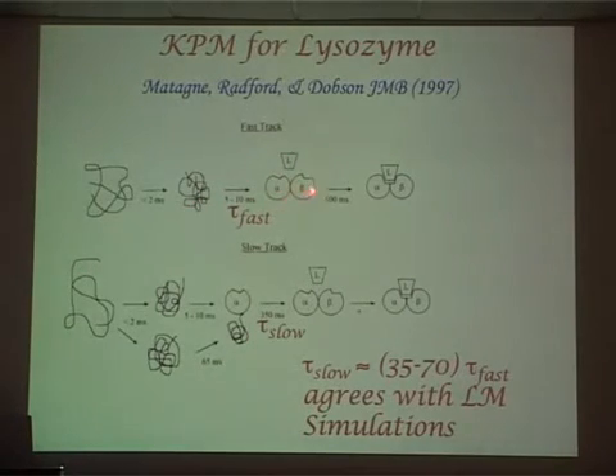Actually, Kiefhaber was the first to do this, but this is an experiment from their paper in JMB in 97. They looked at lysozyme folding, from the unfolded state to the folded state. They do find these fast track molecules, and this is just ligand binding, so you really worry about this fast time scale, which is about 10 milliseconds, and you see that the slow one is about 70 times greater, and therefore this is exactly what we find in a. You shouldn't be so concerned that I'm not trying to match the lattice to this, but generically, the key point is that the underlying mechanism of lysozyme folding follows this kinetic partitioning mechanism.